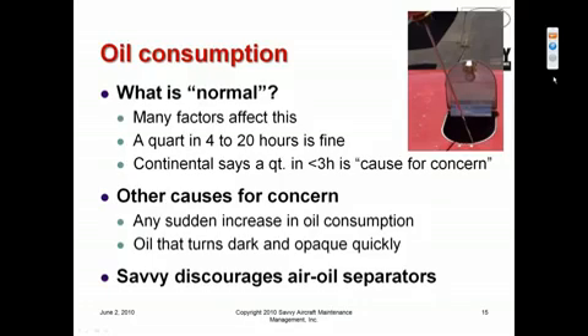Another thing that I like to keep track of is how quickly the oil turns dark and opaque after an oil change. You know, when we first change the oil it is so light and transparent in color that sometimes it's a little hard to even get a dipstick reading, and the oil turns dark as it's in service because we're pumping all this filth into the oil. The rate at which it turns dark is very revealing of how much blow-by there is past the compression rings. And if oil turns dark and opaque very, very quickly, say within a few hours after an oil change, then that's a pretty good indication that we have excessive blow-by past the compression rings, and we probably want to do some stuff like compression tests and borescope inspections of the cylinders to figure out which cylinder or cylinders are the culprit and how serious the problem is.